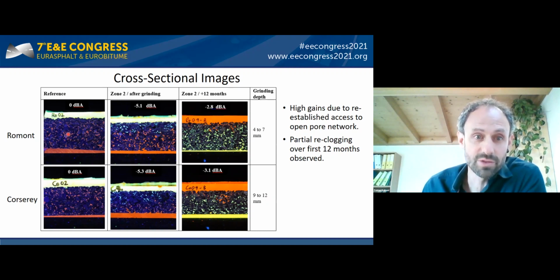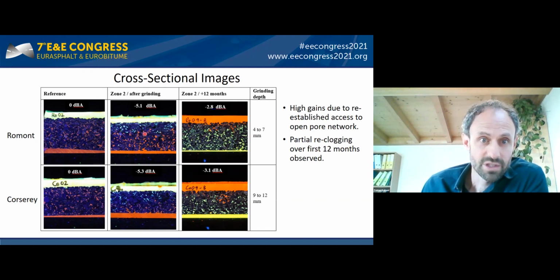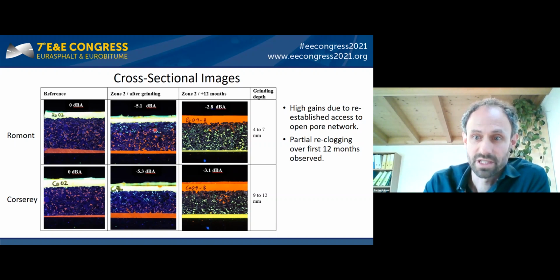The first image was taken as a reference without grinding, the second one immediately after grinding, and the third one 12 months later. It is seen from the reference that no penetration from the resin from top occurs, meaning that the pores were fully clogged. Afterwards, after grinding, there's a significant difference that now the resin applied from top penetrates the porous network.